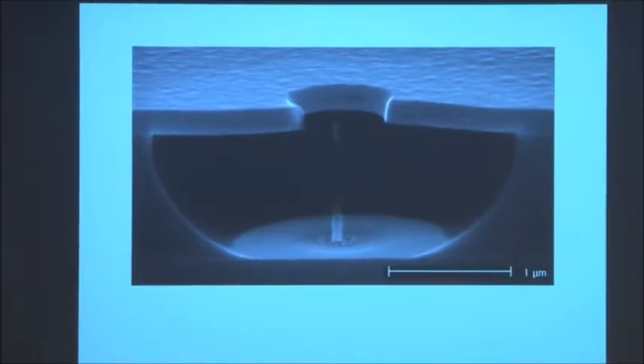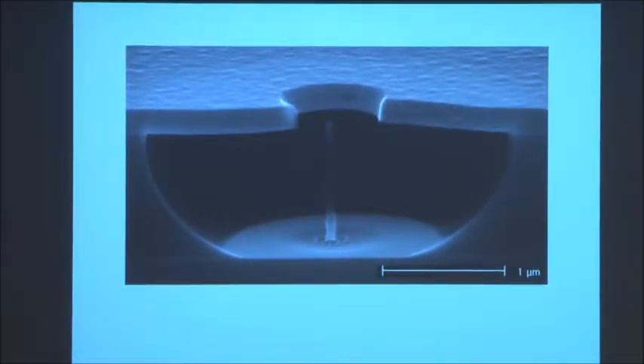For some other applications, we want to be able to control electron emission from the tip of the nanotube. So we put a bias up here, drag out electrons. And so what we want to do is to actually have a gate to control this. So we've used exactly the same kind of procedures as you use in self-aligned process in CMOS. You have here an individual single nanotube in a polysilicon gate. That's not easy to do, but you can do it if you have enough PhDs and enough time.